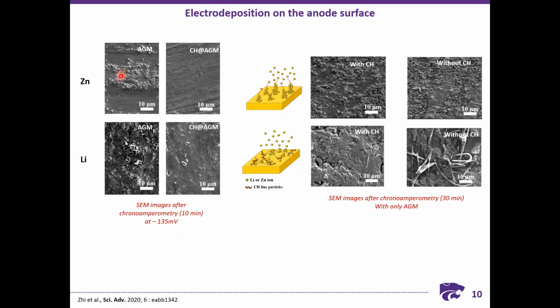So as you can see from here, for the zinc cells with only AGM, we can see the formation of inhomogeneous deposition of the zinc metal, while when they have used the interlayer, there is a very uniform deposition. Similar behavior is seen in the case of lithium metal also.